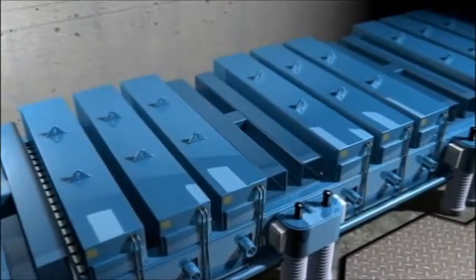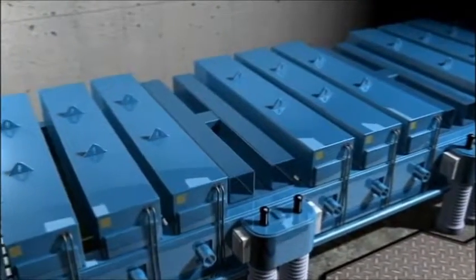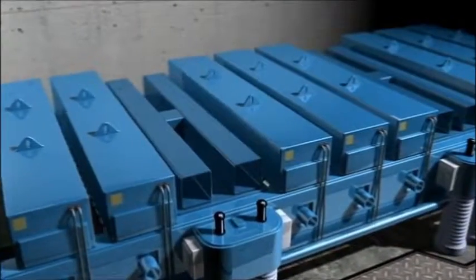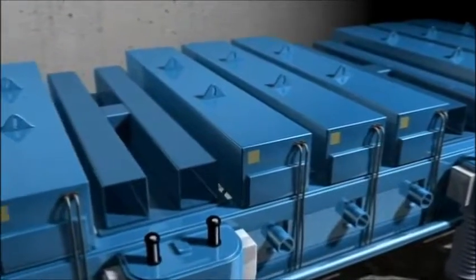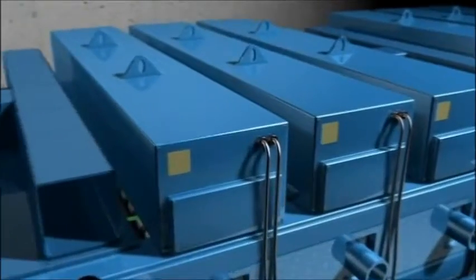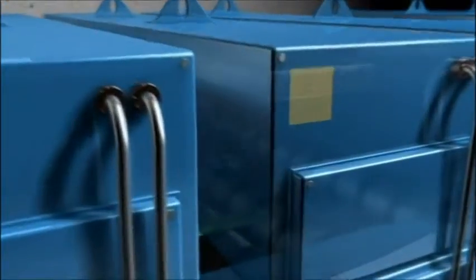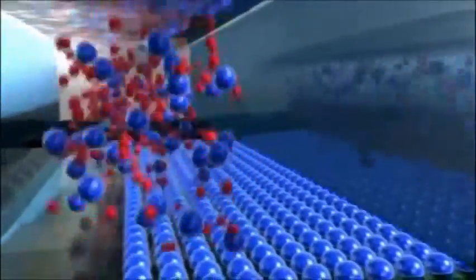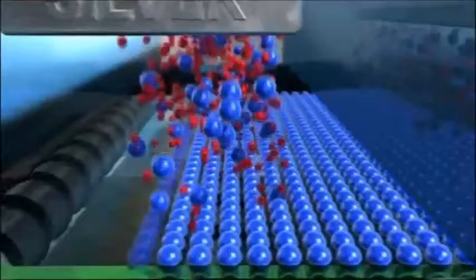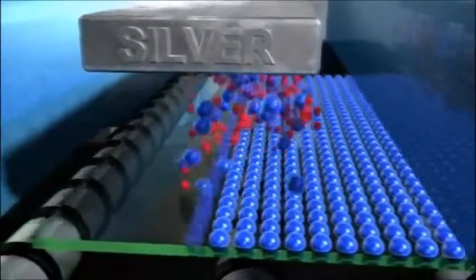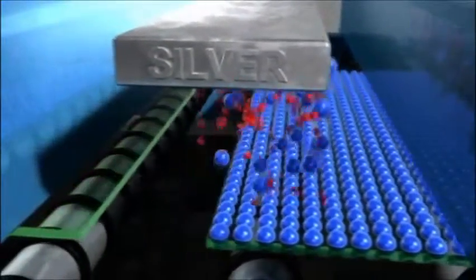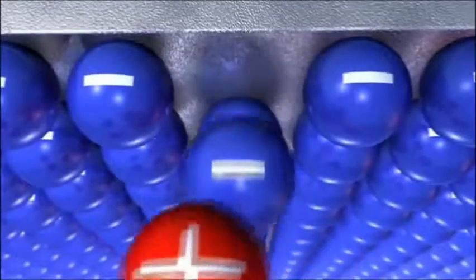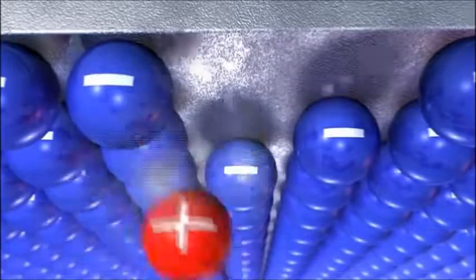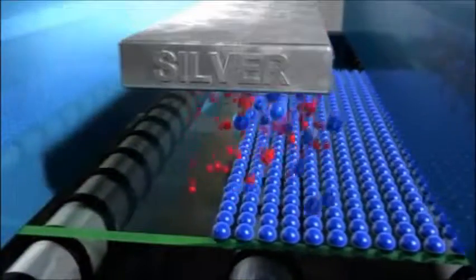In the coating plant, after the glass is washed, the lites are coated in a process called sputtering. This process deposits a thin film of metallic and non-metallic elements on the glass. Inside the coating chamber, positive ions in glowing plasma are attracted to the negatively charged target, for instance, a solid silver bar. The ions strike the target with such force that material to be deposited on the glass is ejected atom by atom, a lot like a cue ball hitting a rack of billiard balls.